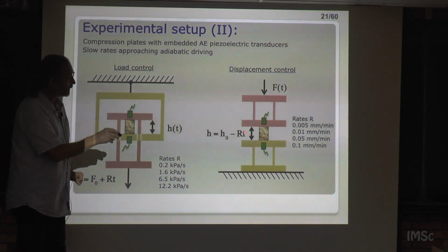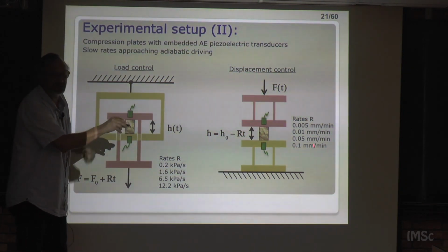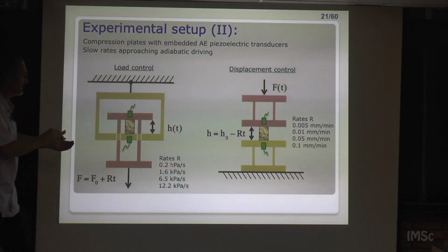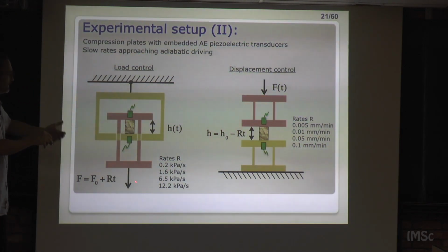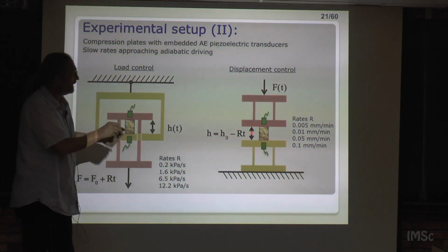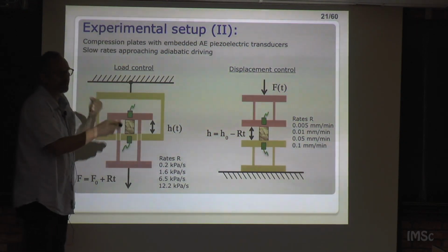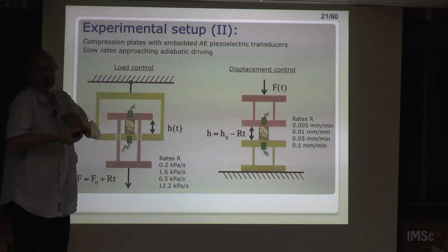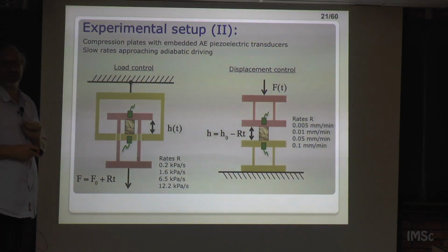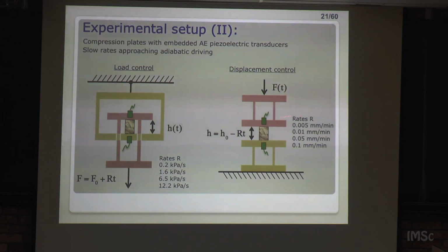It decreases proportional to time with a rate that is millimeters per minute. Here the rate was kilopascals or newtons per second or per minute. This is millimeters per minute. And then what we measure with a load cell is the force needed to keep that rate going on, okay? So these are the two different ways we will do, and we sometimes compare the results of the two different experiments.